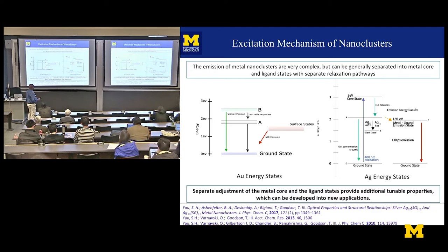But then, of course, you still have energy transfer to these surface states or metal ligand emission states. But then you get a relaxation that's on the order of 130 picoseconds. This looks like emission from a dye, okay? Somehow that suggests that you are making some kind of surface state that has emission that looks like a dye. Okay, so we said, well, that's interesting.